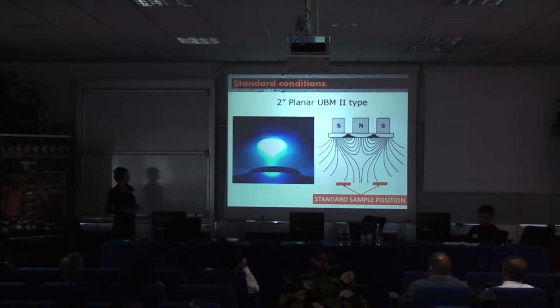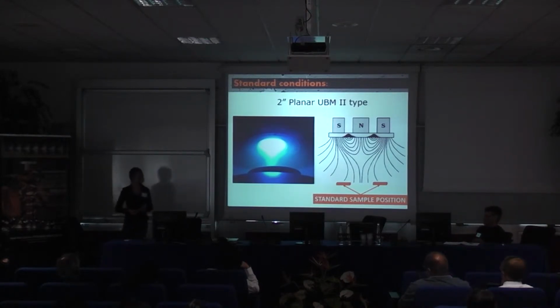We have deposited niobium by a 2 inch planar magnetron of the second type of unbalancement. It means that in a planar magnetron, the external magnetic ring is stronger than the internal one, and you can see something like an elongation of the plasma on the central axis of the magnetron towards the substrate. Standard placement of the samples was not exactly behind the plume and not far near the wall of the chamber, somewhere here.